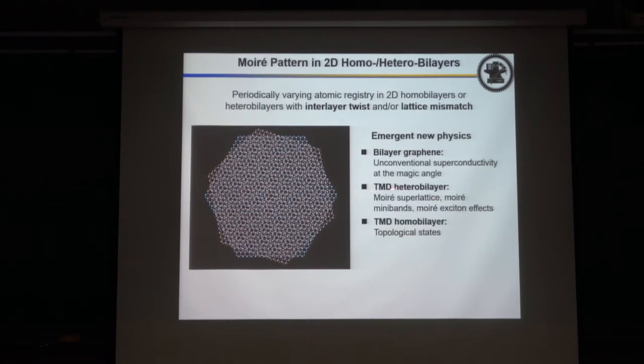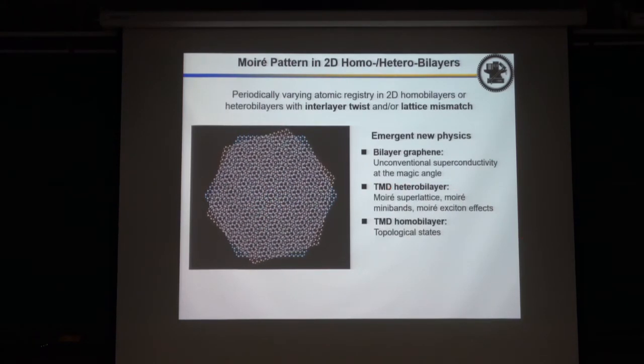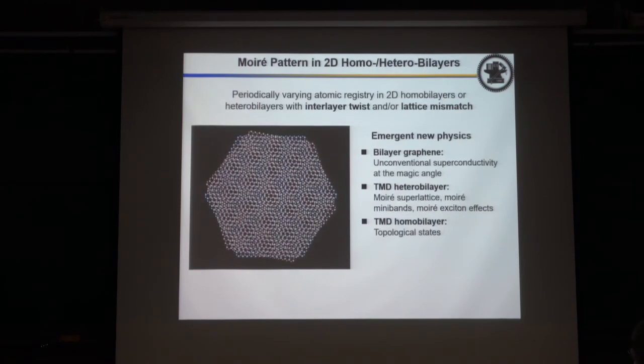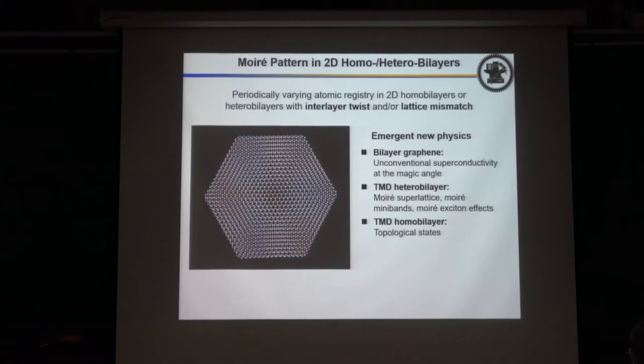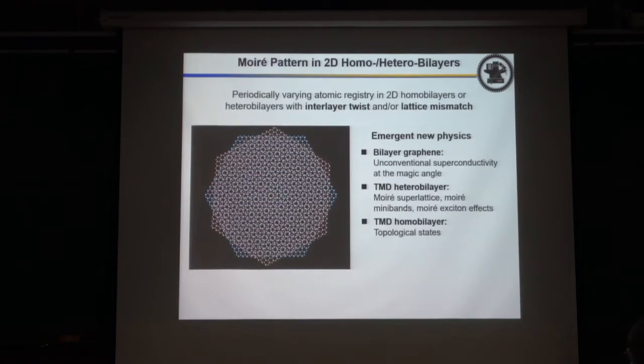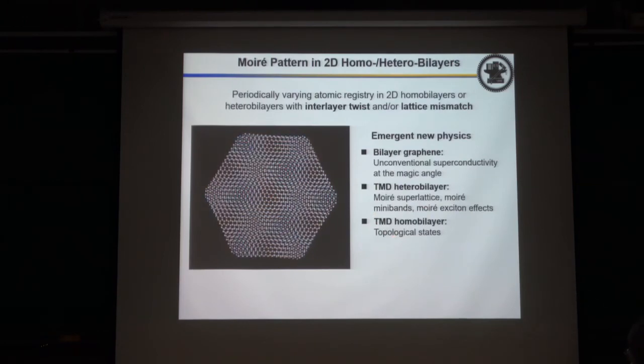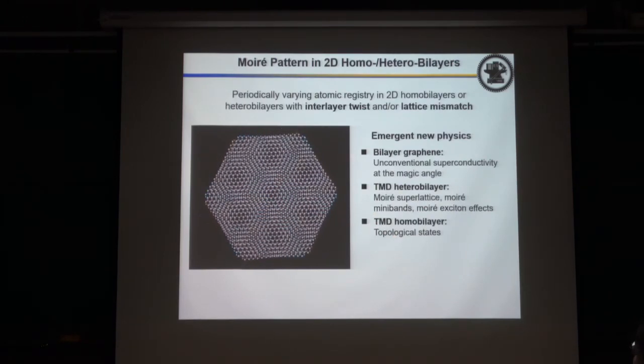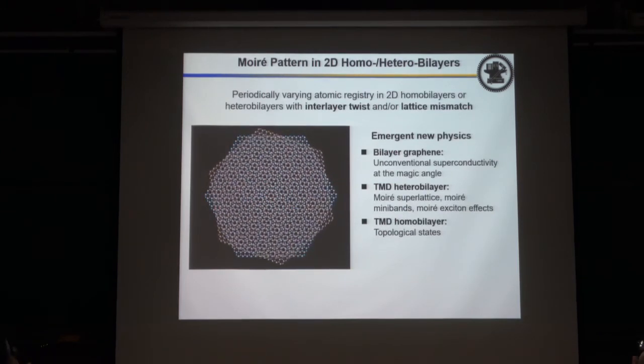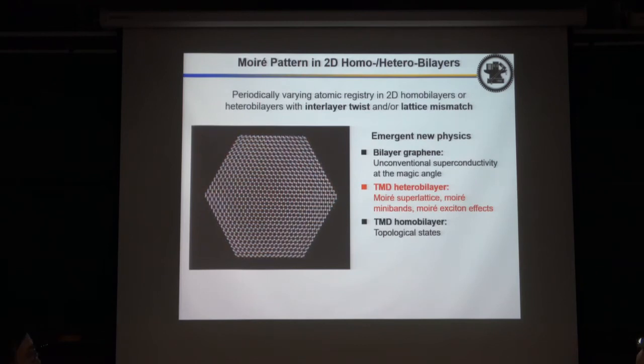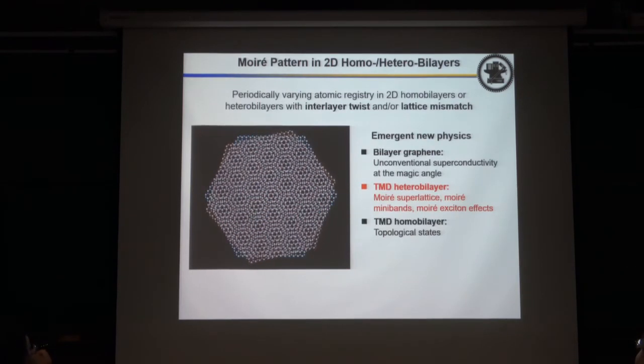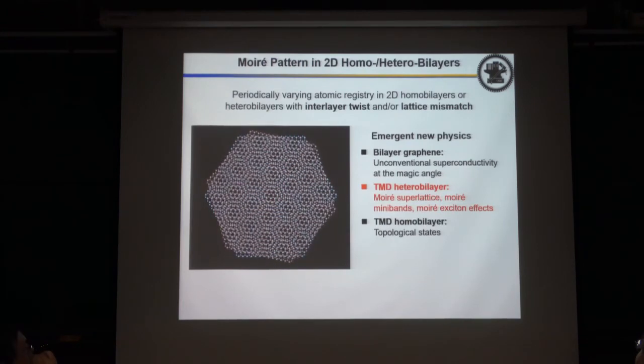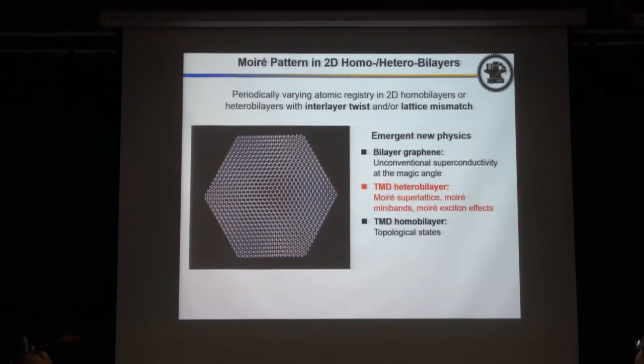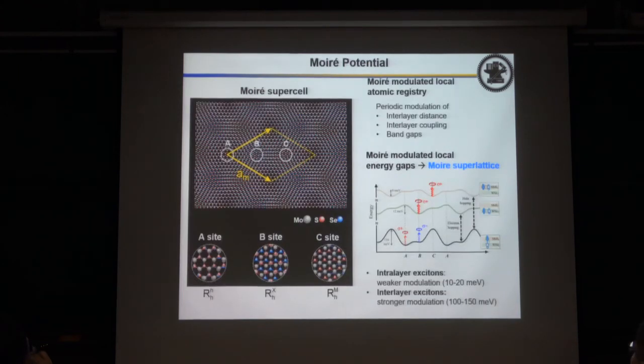And also in TMD material, we can use the Moiré pattern or Moiré superlattice to modulate the exciton dispersion in the material, because we impose another periodicity on the exciton or carrier. And they can also create some so-called topological state in TMD bilayer with Moiré pattern. So we also use our CVD-grown samples to study the so-called Moiré superlattice and their effect on the Moiré miniband, Moiré exciton effect. So let's take a closer look at the Moiré supercell.